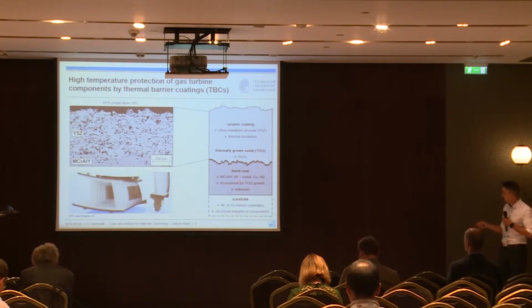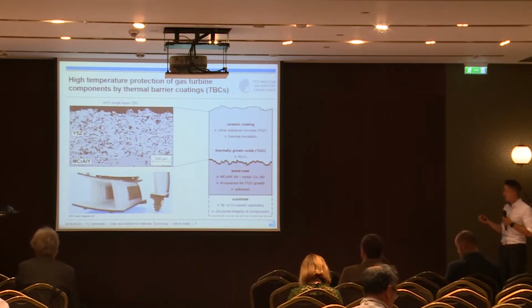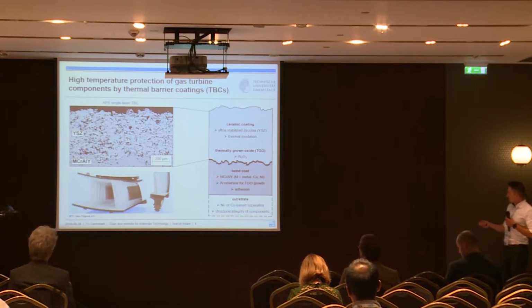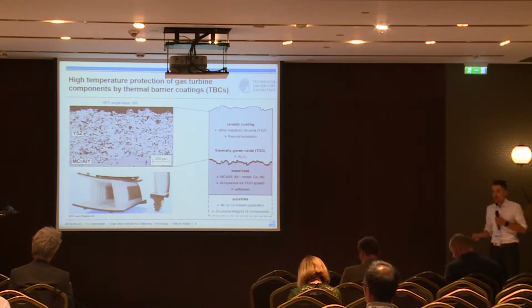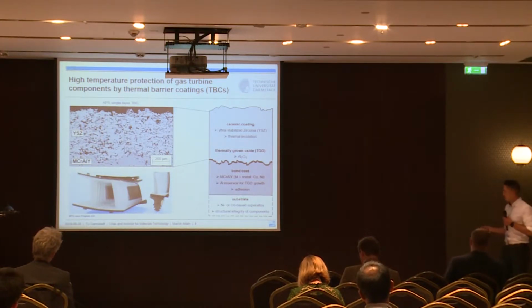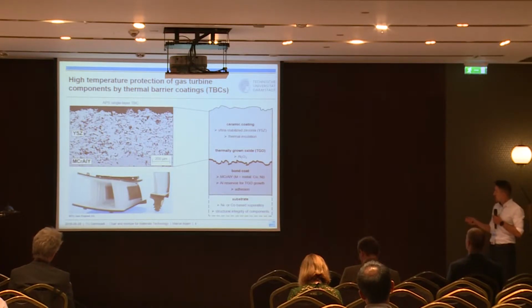On top of that, we find a bond coat layer, which is normally made from MCrAlY, where M stands for cobalt or nickel or a composition of both, with chrome, aluminum, and yttrium. It provides adhesion between the ceramic coating and the substrate. On top of that, we find a ceramic coating, normally made from yttria-stabilized zirconia, or YSZ. This provides the thermal insulation.